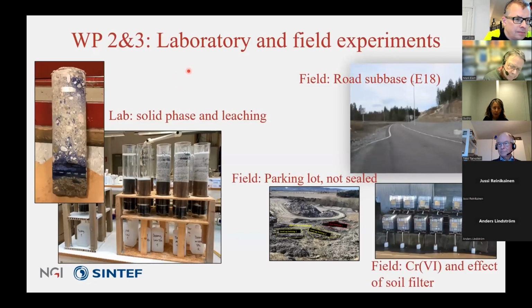And these laboratory and field experiments were quite important. Also, I don't remember who it was, but someone mentioned that it's not only about calculating the risk, it's also about giving trust, in this case to the environmental authorities, to show that what we model is also what we maybe get in real life. So we took a lot of solid samples, leaching tests, both batch and column testing. We had several field tests, like this road subbase, which SINTEF had been following since 2004.